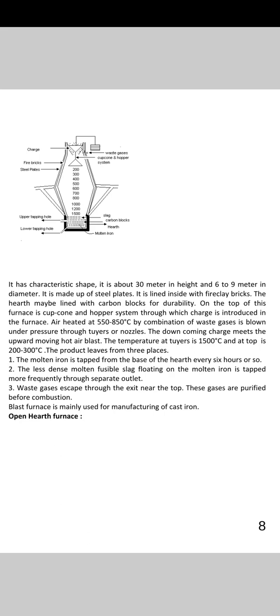The down-coming charge meets the upward moving hot air blast. The temperature at the tuyeres is 1500 degrees Celsius and at the top is 200 to 300 degrees Celsius. The product leaves from three places. The molten iron is tapped from the base of the hearth every 6 hours. The less dense molten fusible slag floating on the molten iron is tapped more frequently through a separate outlet. Waste gases escape through the exit near the top. These gases are purified before combustion. Blast furnace is mainly used for manufacturing of cast iron.